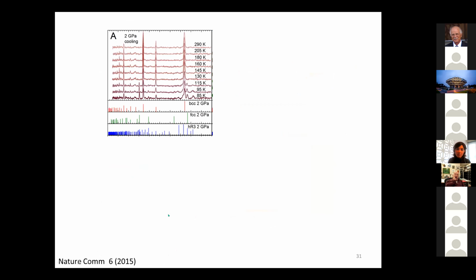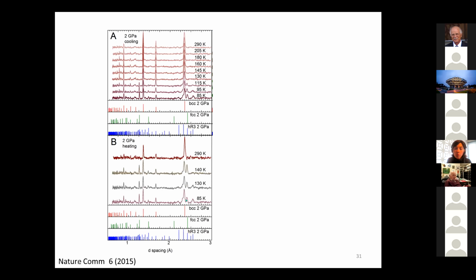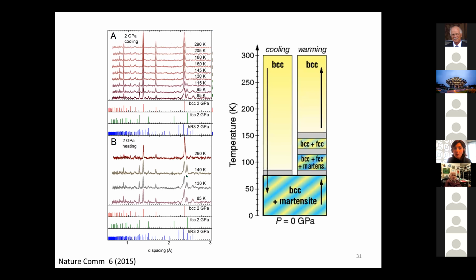I'm going to walk quickly through these. These are neutron studies in a Paris-Edinburgh cell that we did at Oak Ridge National Lab. Here you can see that as I cool down the lithium at 2 GPa, it starts to have extra peaks that overlap with the 9R or Martensite. So we enter the 9R phase. Now, as I warm it up from 9R, I start to see a mixture of FCC and BCC, and 9R goes away. I want to compare it with these early studies from 1990 that see the same thing. You go from BCC to 9R, but when you warm up, you recover some BCC and FCC.